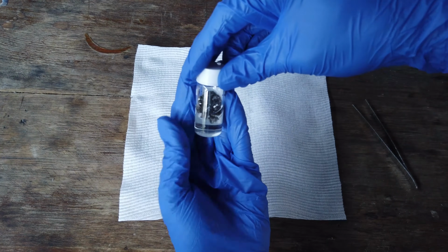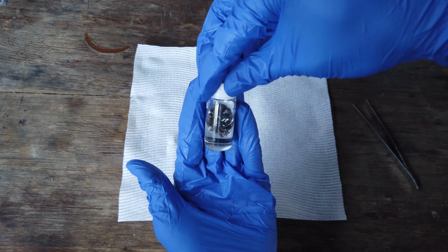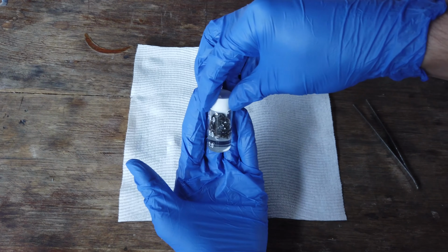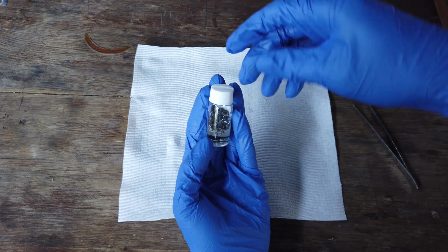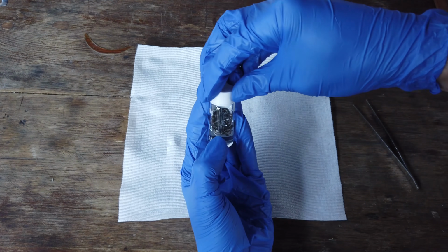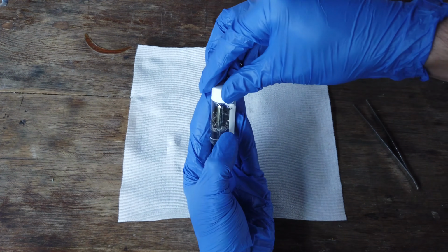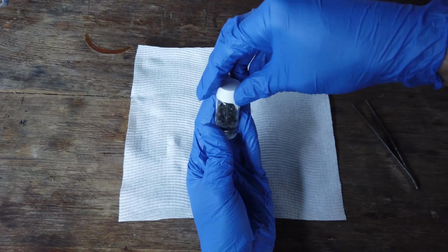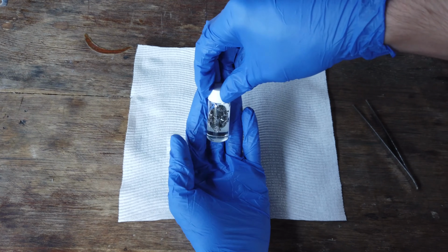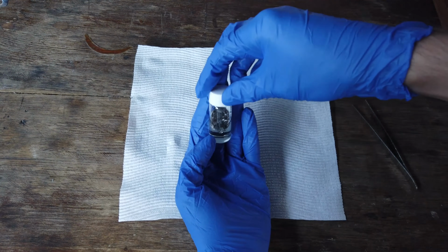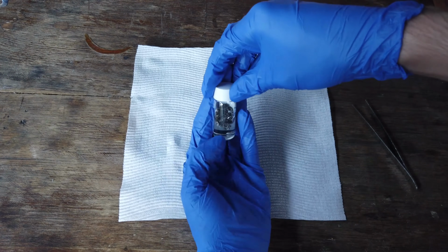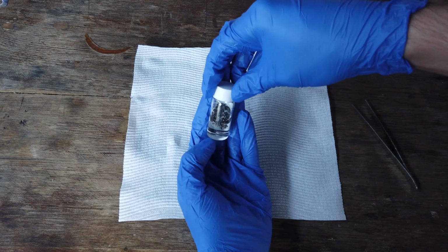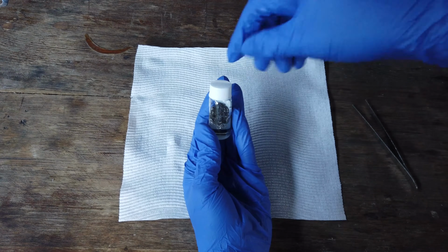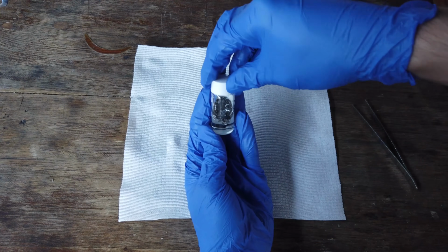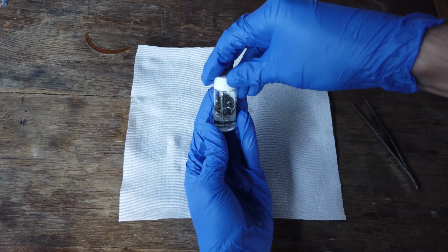And last but certainly not least, we do actually have the total lithium yield we were able to obtain from the process. You can see there, that's quite a sizable amount, I'd say. Of course, we weren't able to melt it all into one droplet, so that was a little bit disappointing. Also, you can see we have a few shiny bits, maybe down the bottom there, and around the edge there, but a lot of them have turned black. That is, of course, due to the nitride coating on the lithium surface that forms in contact with air, because lithium reacts with both oxygen and nitrogen from the air, and the fact that it floats on mineral oil means it's really difficult to stop that from happening. Maybe I could push it down to the bottom with a bit of fiberglass or something to prevent it from just sitting on the surface, but I'm probably not going to bother doing that.